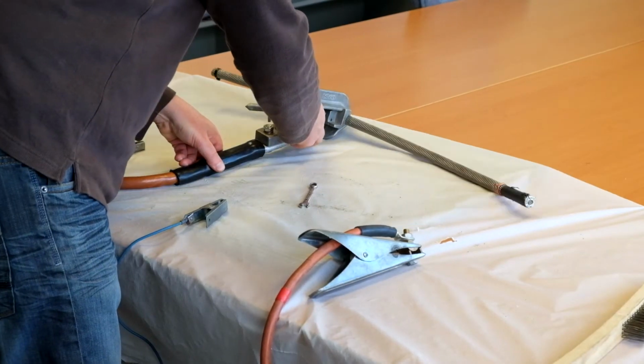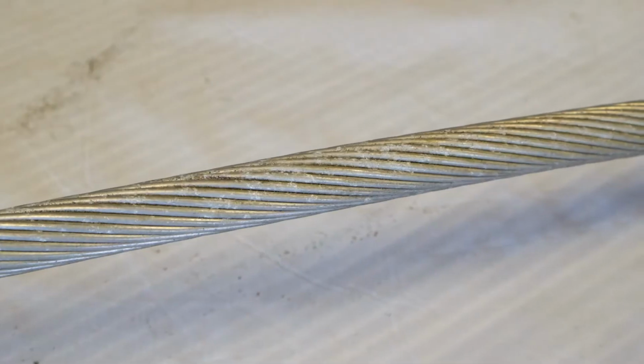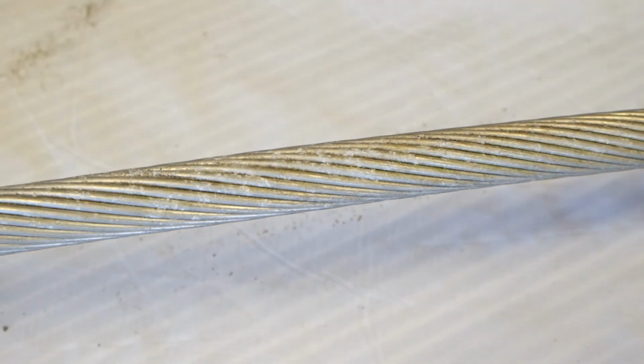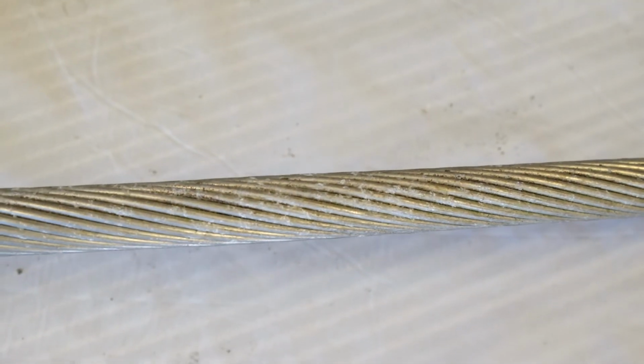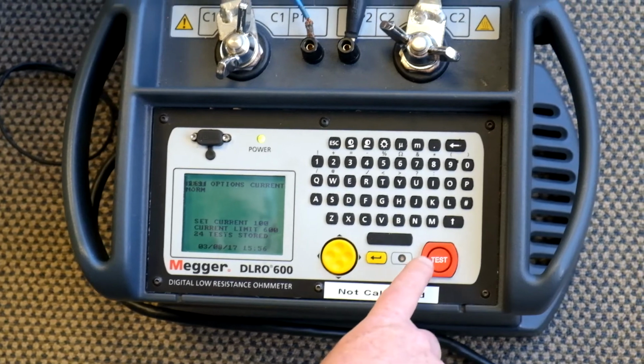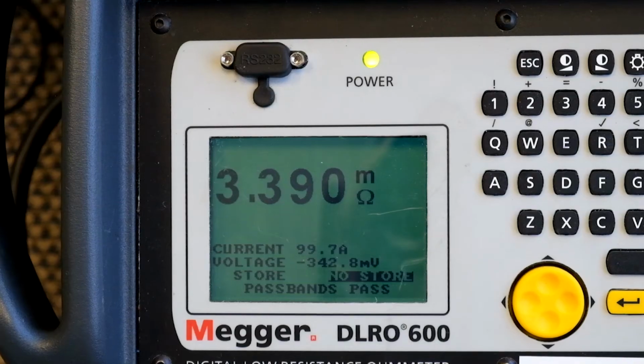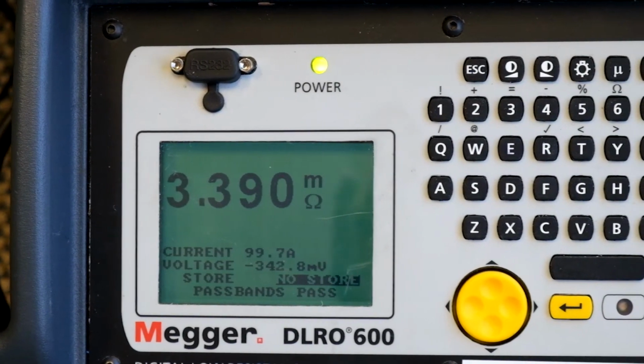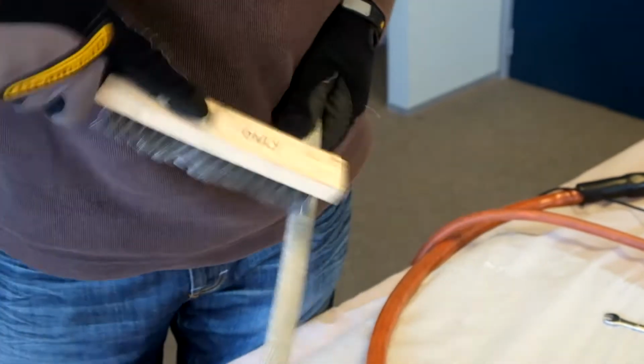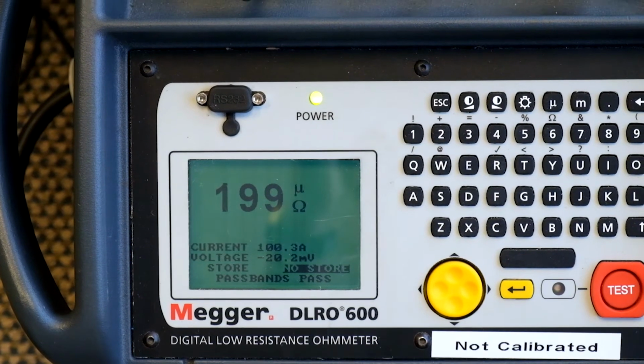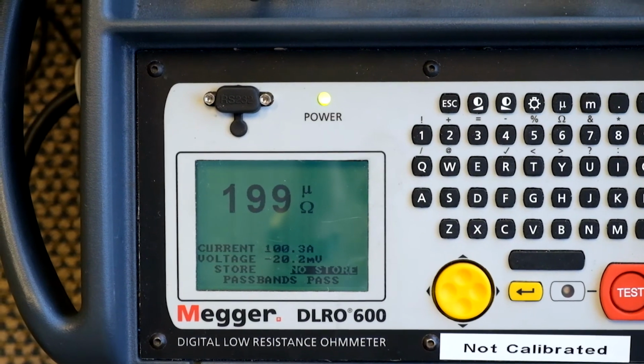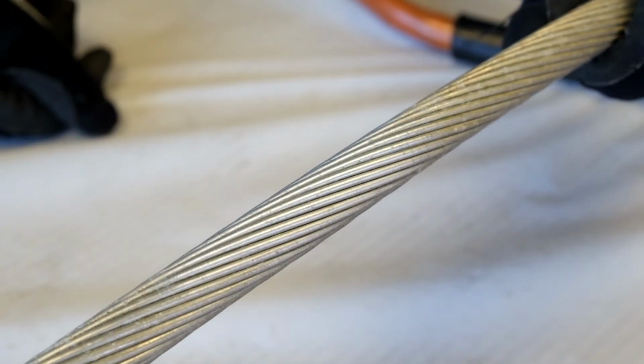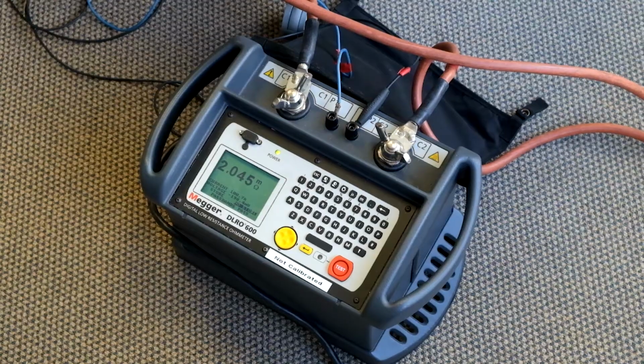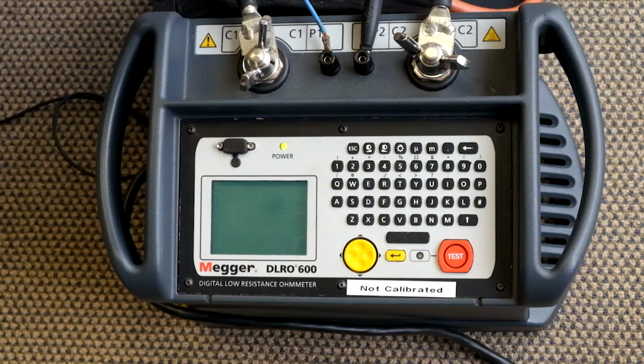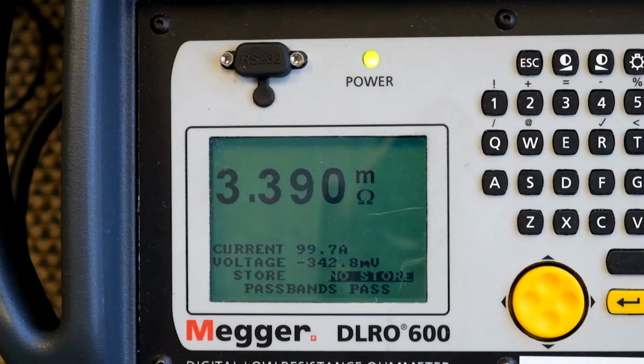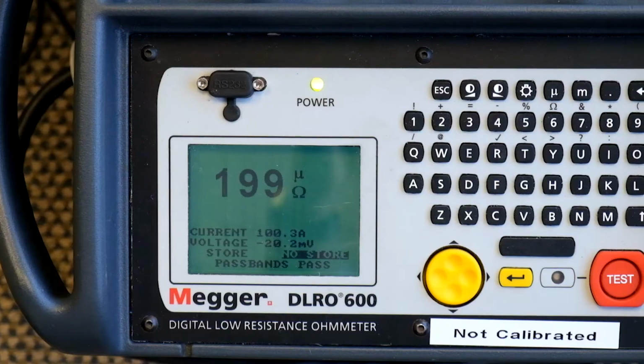Conductor 2. The next conductor sample is also a piece of aluminium conductor, but this example shows visible contamination on the surface. The first result before cleaning is 3,390 microohms, while after a clean with a wire brush, the result drops to 199 microohms. Again, a reduction to just 6% of the uncleaned value. Both of these results show what a big difference just 20 to 30 seconds of cleaning can make.